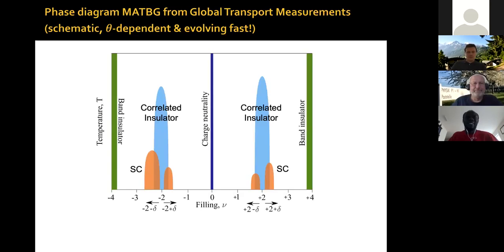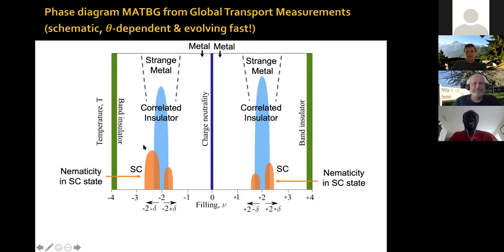We have the following. We have realized that there is a region of strange metal behavior, linear in temperature resistivity, around the correlated insulator states. And this is very reminiscent of the strange metal behavior in many correlated materials. Whereas, for example, near charge neutrality, you have regular metallic behavior. The superconducting state exhibits anisotropies, which lead us to conclude that there is a nematic superconducting state. There is a competition between different orders along the superconducting state. And there are also regions of nematicity in the normal state. Okay, these are things which I'm going to be telling you about today.